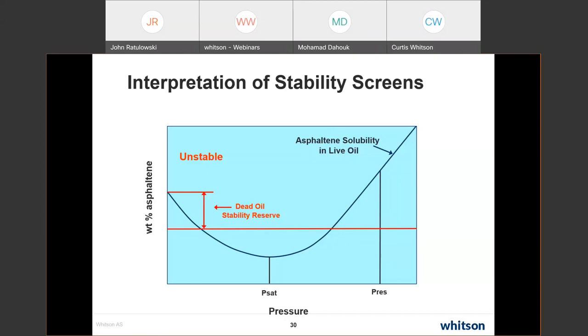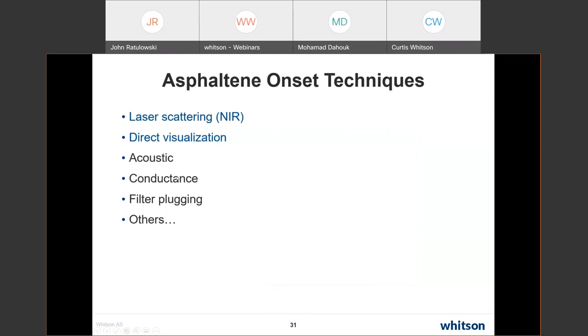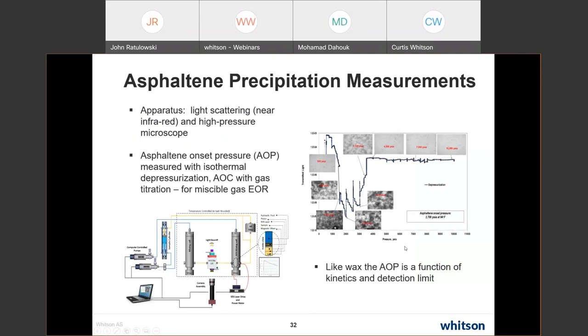So asphaltene onset, we do measure that. The type of measurements we do that have become fairly standard in the industry is laser scattering. It's an NIR laser and direct visualization through high pressure microscopy. In the past, other methods have been tried. Acoustic conductance, interestingly enough, nobody, I don't think, really understood why that worked, but it seemed to work. Filter plugging, which is not as sensitive as a direct visualization or the laser scattering. And I'm sure there are others that I have missed in this overview. So asphaltene precipitation measurements, these are fairly standard now. Each lab has a slightly different configuration.